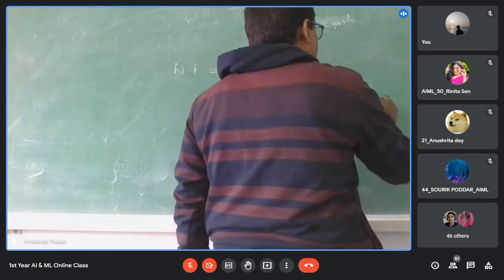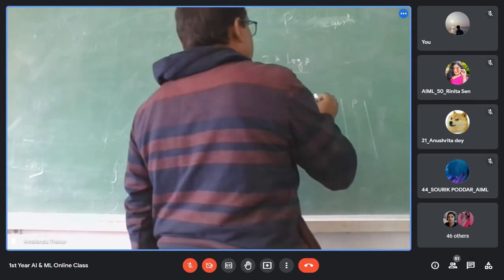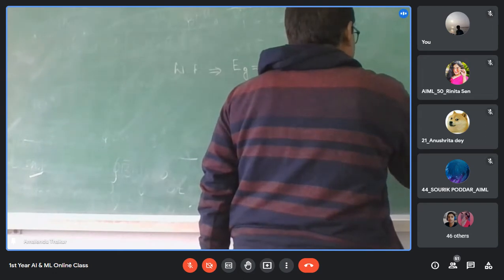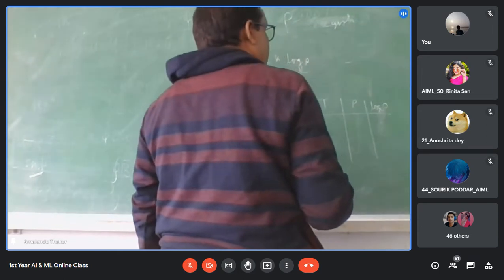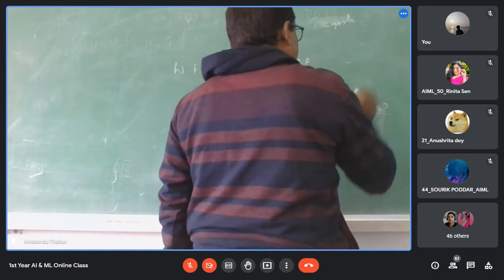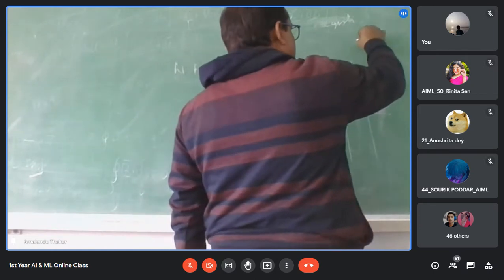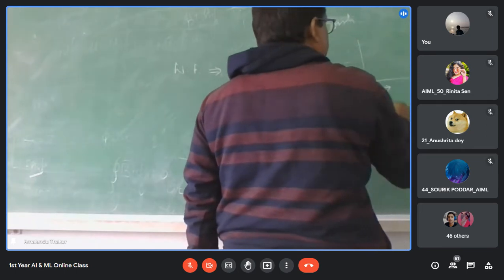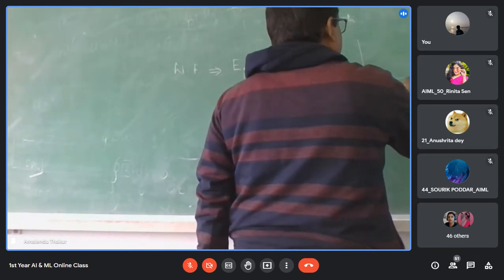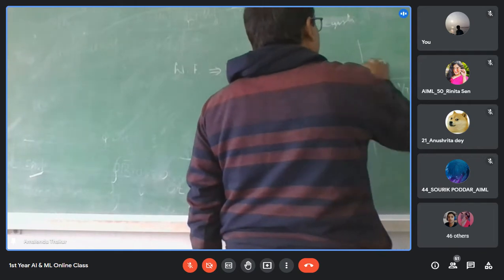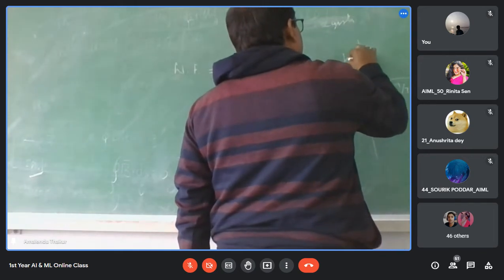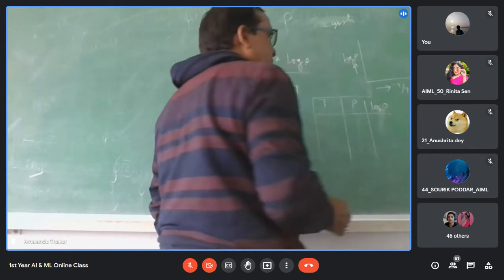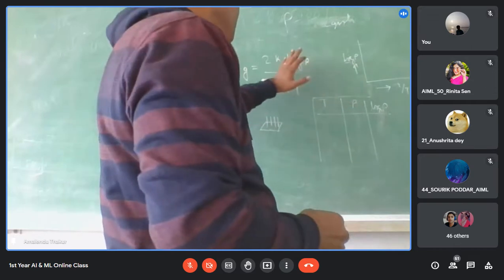and from there we convert to the log value of this rho. Then we draw a graph: along the x-axis we consider the inverse of the temperature, and along the y-axis we consider the log of this rho. So we will get a curve. From there, we take the slope of this curve and put the value.